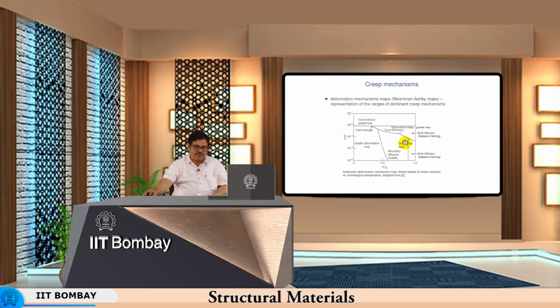You have diffusional flow at high temperatures, low stresses, and then dislocation creep due to core diffusion, meaning diffusion along the grain boundaries and vacancies aiding the climb of dislocation. So, dislocation creep, but then dislocations are able to climb due to high stresses, vacancy migration due to high stresses, and due to some diffusional flow as well.